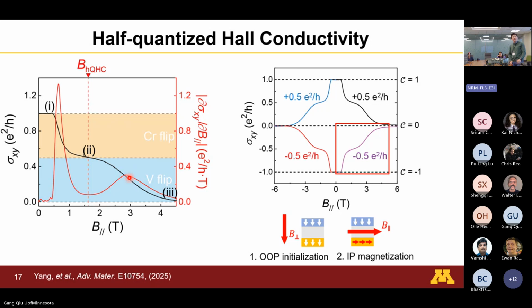The other question is the temperature requirements. Right now, the record is maybe 2 Kelvin or 4 Kelvin to reach a very good quantization. But that being said, there's no fundamental limit why this only happens at low temperature. In fact, the first theoretical prediction says we can do that at 30 Kelvin. Our group tried, but for some time we didn't see that, so we just gave up. And then another group in China actually put this thing at 20 millikelvin. They saw it first. So the theory is right on the big picture, but they didn't tell us these details.